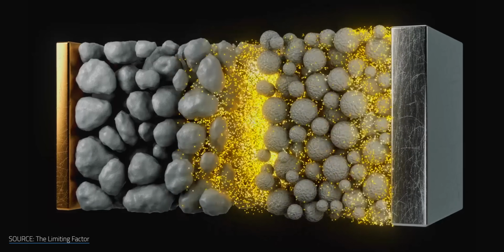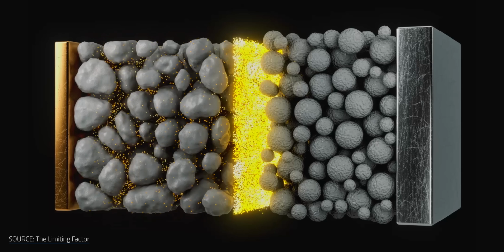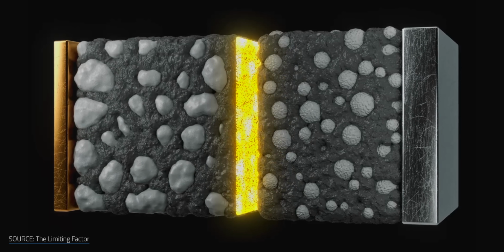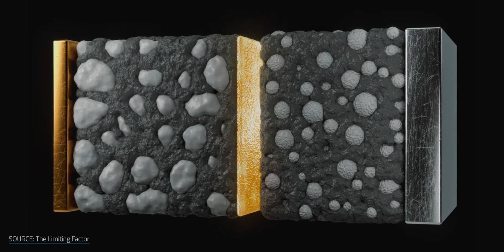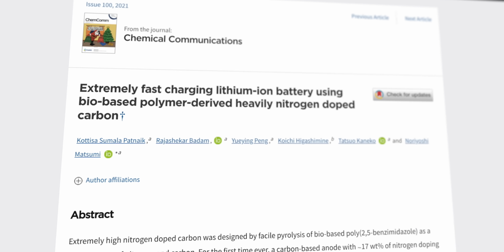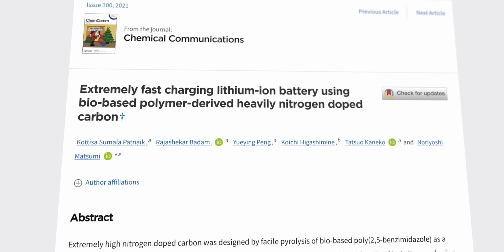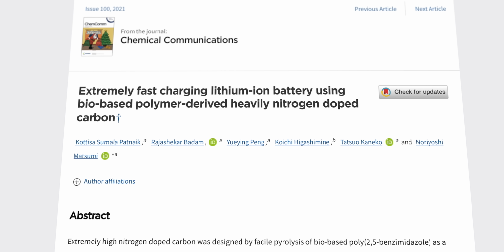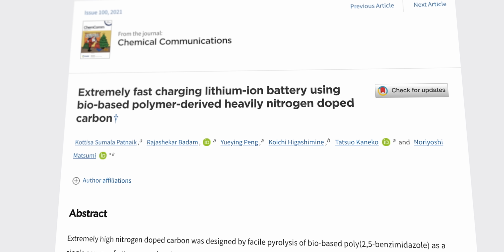This leads to the formation of a solid layer over the anode surface, which slows down the movement of lithium ions, which limits the charging rate of the battery. Now, for this reason, researchers have turned to bio-based carbon sources to replace graphite in the battery anode. Last year, a Japanese group harnessed a biopolymer to make a battery anode and achieved a shorter charging time compared to those obtained using a graphite.